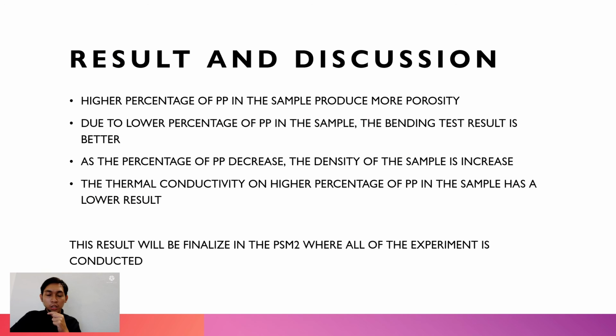For the last part of this presentation, I will present the result and discussion. The first one is that a higher percentage of polypropylene in the sample produces more porosity. Due to a lower percentage of polypropylene in the sample, the bending test result is better. As the percentage of polypropylene decreases, the density of the sample increases. And the last one is that the thermal conductivity of a higher percentage of polypropylene in the sample has a lower result.